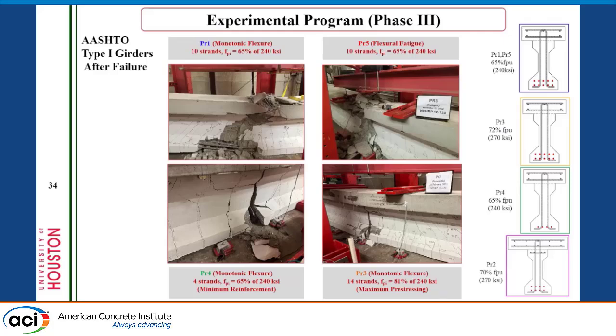The first two on the top, basically we designed them to have strand rupture, but because of the lack of concrete strength that we got in the precast plant, our design concrete was 9 KSI, but we got only 7. So we got concrete crushing on the top. And the ones on the bottom were exactly what we designed, and we got a strand rupture.